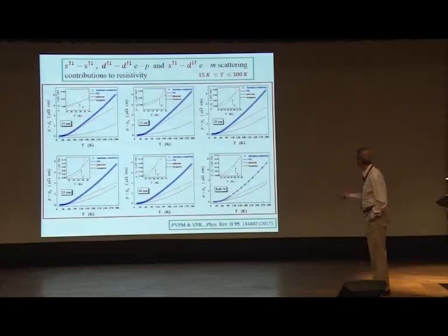When the crystallite size is low, the major contribution is coming from the electron-phonon scattering. Electron-magnon scattering is not doing much, with a factor of 2 or so difference between them. And this is picking up now.